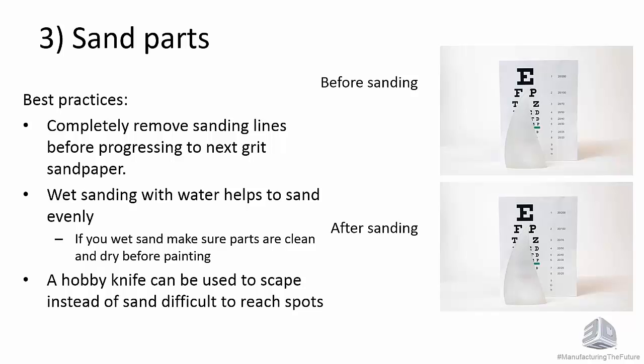Another thing we recommend is wet sanding with water. So you have to get sandpaper that's wet or dry. And what it does is it helps you do a more even sand. You're less likely to gouge, or it just gives a better consistent sanding. And if you do wet sand, the one thing is you have to make sure the parts are clean and dry before painting. Make sure there's no dust or particles. And so usually just wash it off either with water or IPA, some people use.